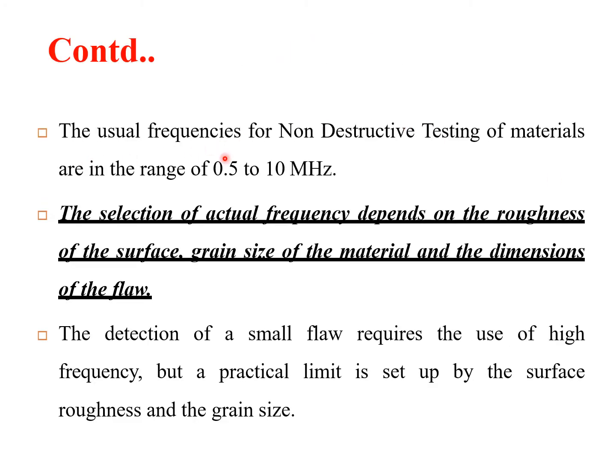Now, the usual frequencies for non-destructive testing methods are as follows. In the ultrasonic testing method, the usual sound frequency is between 0.5 to 10 megahertz. The selection of the frequency depends on a lot of factors. First one is the roughness of the surface. Second one is the grain size of the material, that is, the material structure. And third one, the dimensions of the flaw.